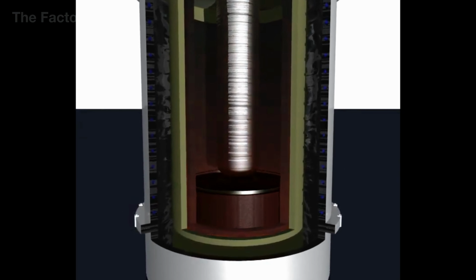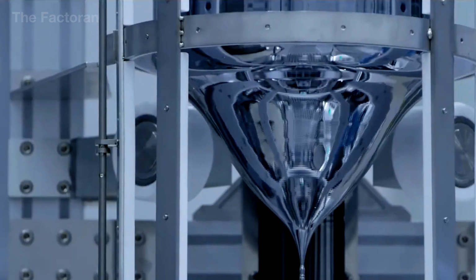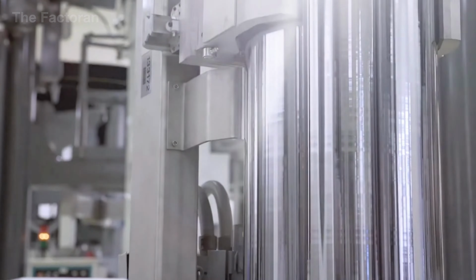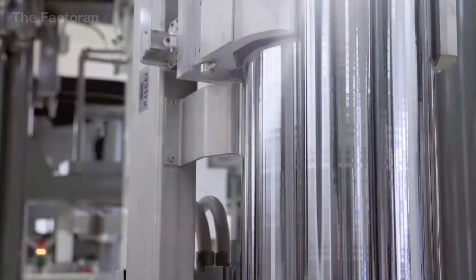An important detail throughout the pulling process is that the distribution of oxygen from the quartz crucible into the silicon is tightly controlled. When kept within an optimal range, this oxygen improves the mechanical strength of the wafer, but if it exceeds the limit, it can introduce microscopic defects that affect transistor performance later on. The final result is a single crystal silicon ingot measuring 3 to 6 feet in length and weighing hundreds of pounds with an almost perfectly continuous atomic structure.